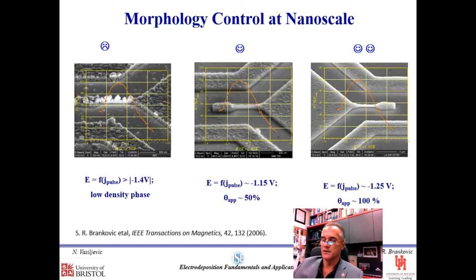For example, on the very left, we pretty much don't have any saccharine at the surface because the potential is too far negative, and we do pulsing and we have very rough structures, which are useless. These devices are not performing. Then if we reduce the pulse current density and potential of the surfaces somewhere in the region where additives coverage is about 50%, we see improvement.